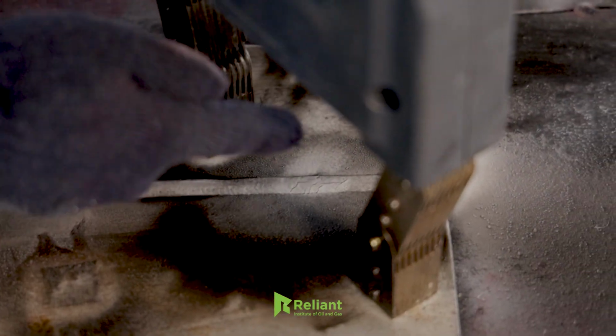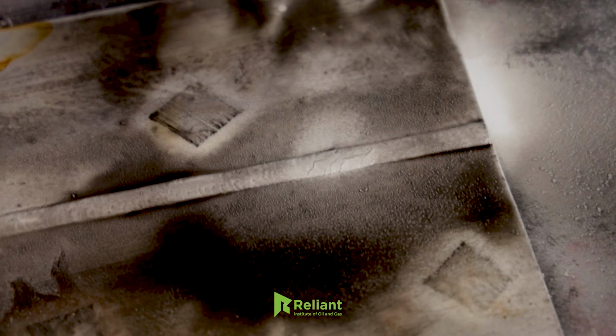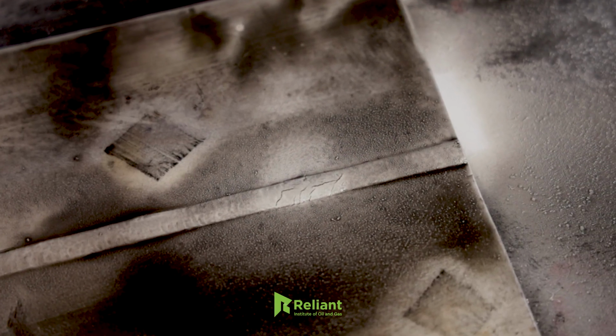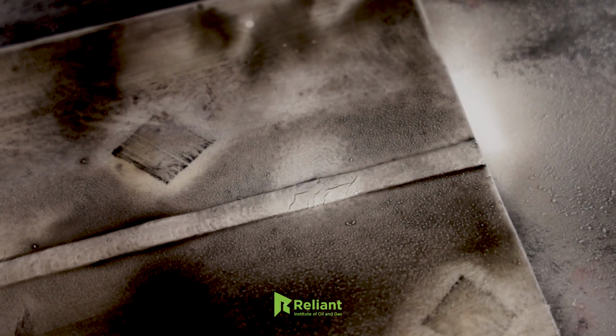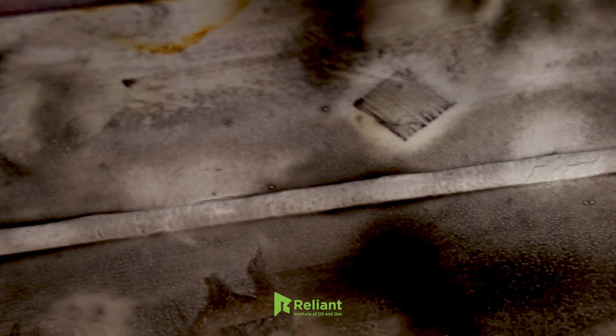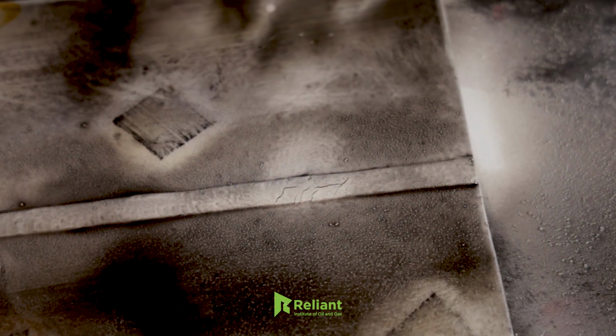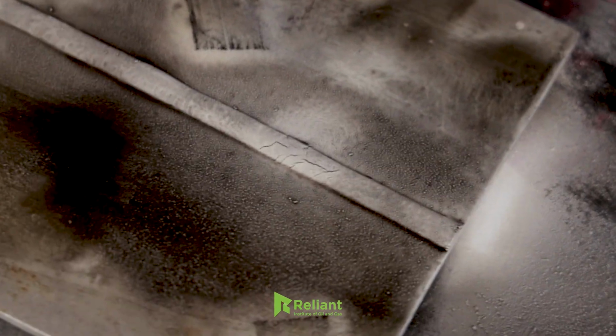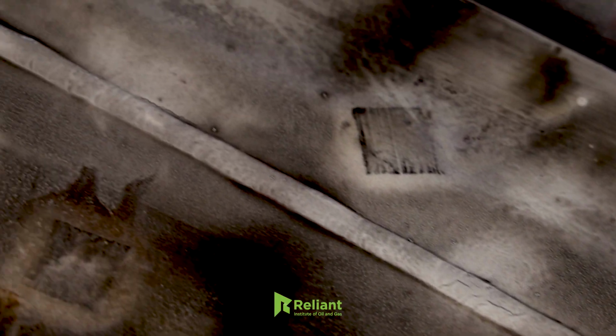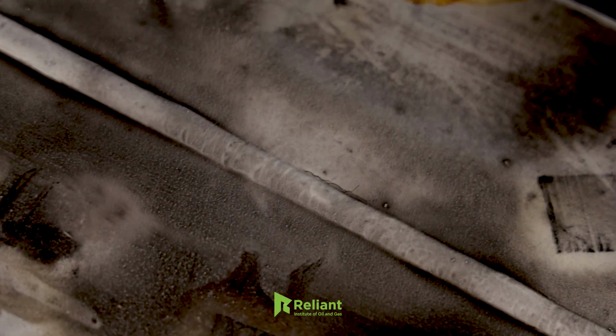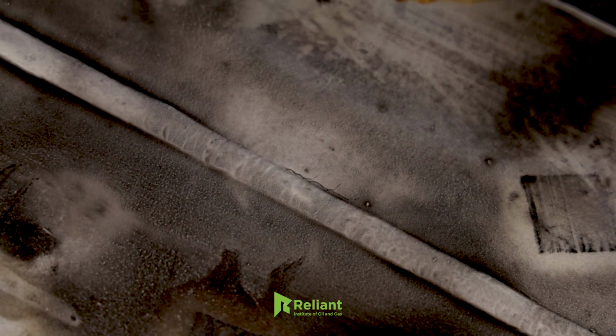So it's very clear that a branching crack has arisen. So we got two indications, one in the parent metal, another one in the weld metal. So one parent metal longitudinal crack, another one is a longitudinal branched weld metal crack. So now, in the case of a pipe, I'm going to conduct the testing.